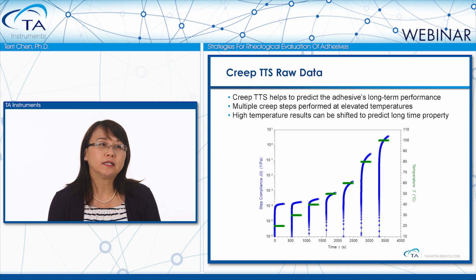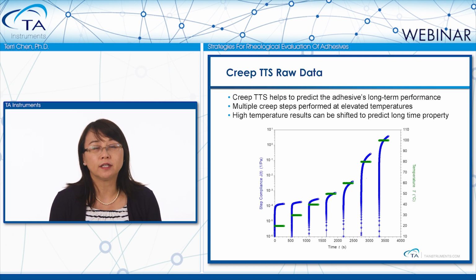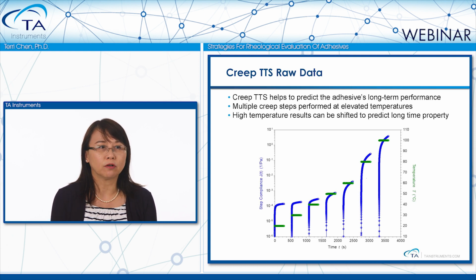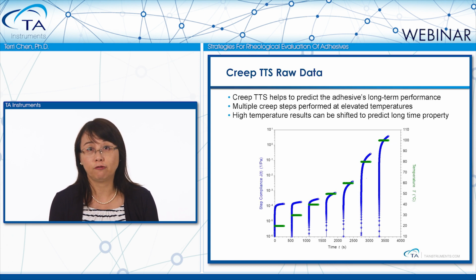In order to predict shear resistant property of an adhesive over a long time, such as months or years, a creep TTS experiment can be performed. It is a multiple-step creep experiment conducted at elevated temperatures starting from your reference temperature. The high-temperature creep results can be shifted and also used to predict long-term performance.